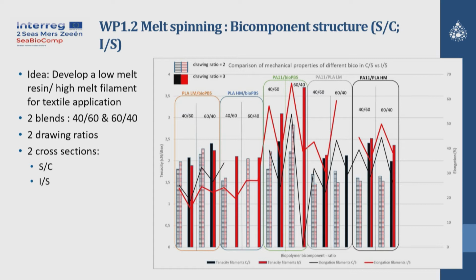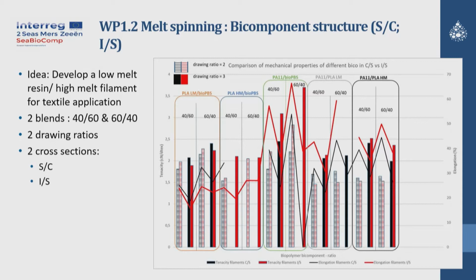We tried core-sheath and islands-in-the-sea structures in melt spinning, and what appears from this study is that PA11 with bio-PBS seems to be one of the most appropriate couples of polymers. But not only that, we have also seen quite a difference in the structure. There is an increase when we draw more, but it's normal. And as they have observed at Centexbel, when we increase the high melt ratio, we also increase the tenacity, which is quite logical, but when we talk about couples, it's not so obvious.